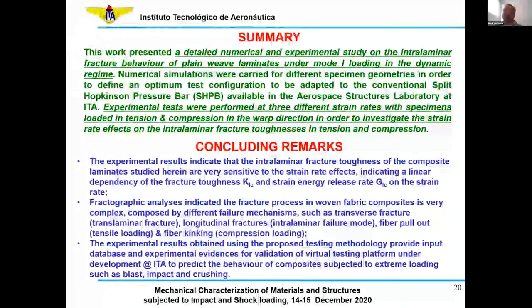And finally, to conclude, as my time is over, this work presented a detailed numerical and experimental study on the intralaminar fracture behavior of plain weave laminates under mode one loading in the dynamic regime. We performed simulations using different specimen configurations in order to define an optimum testing configuration to adapt to the conventional Split Hopkinson pressure bar. Experimental tests were performed at three different strain rates, loading tension and compression, in the warp direction, in order to investigate the strain rate effects on the intralaminar fracture toughness.